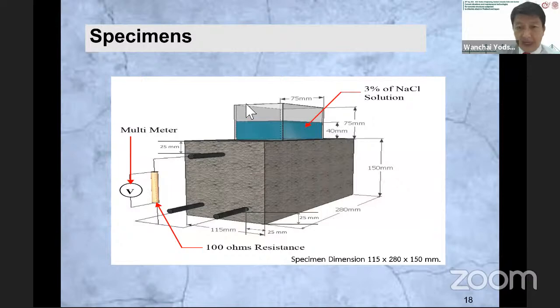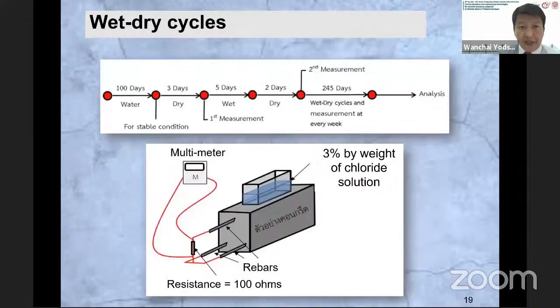And we have a sodium chloride solution container on top of our specimen. And we have three steel reinforcements here. For the wet-dry cycle, after we cure for 100 days and dry for 3 days, we have the first measurement for the corrosion potential and corrosion current. And after wet for 5 days and dry for 2 days, this is one cycle. We have a second measurement, and we continue to 245 days.